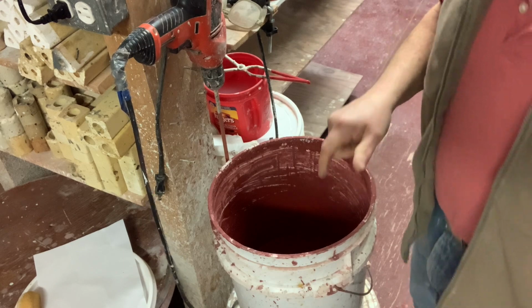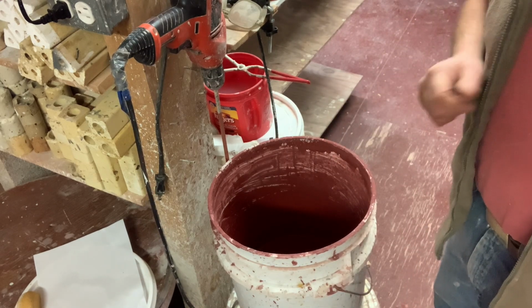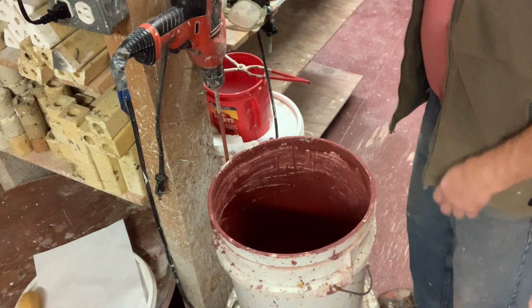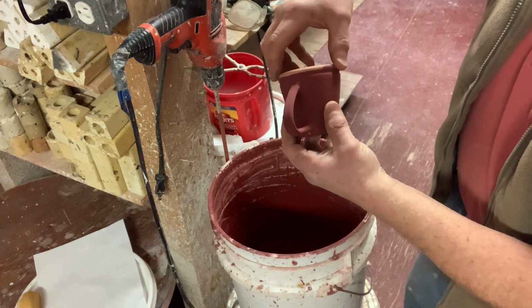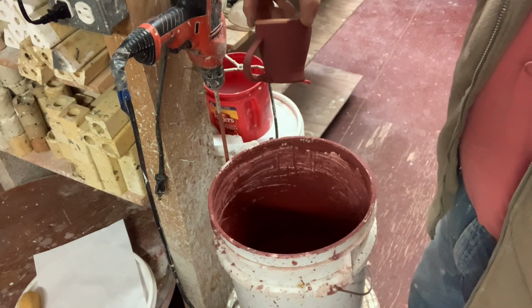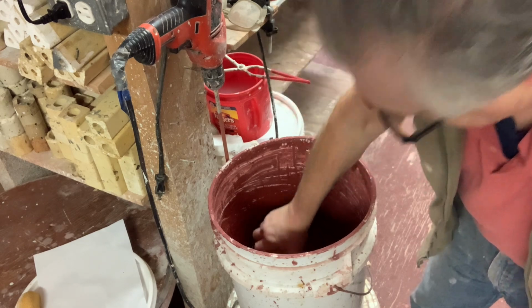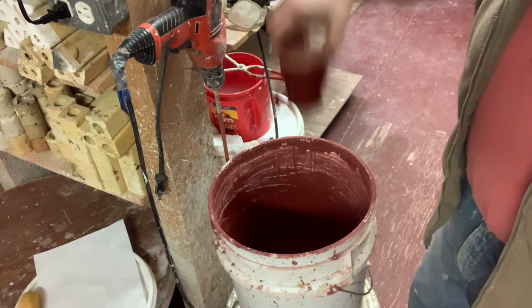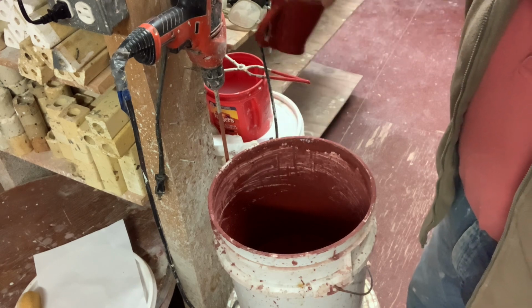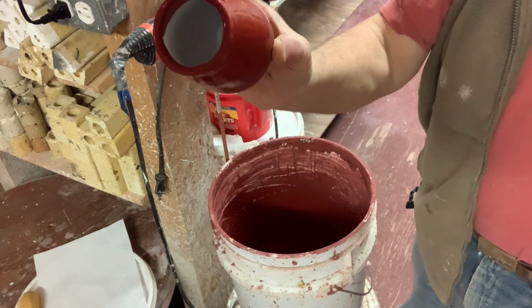Randy's red glaze is really thick, but I've still noticed that I get better reds if it's on thicker. So all I do, I've got the one here with the white on the inside. I'm not going to get it white on the inside, I mean brown on the inside. So I just take it and dip it all the way down and pull it out straight away and knock all the drips off. So you've still got white on the inside, but now we have a double coat.